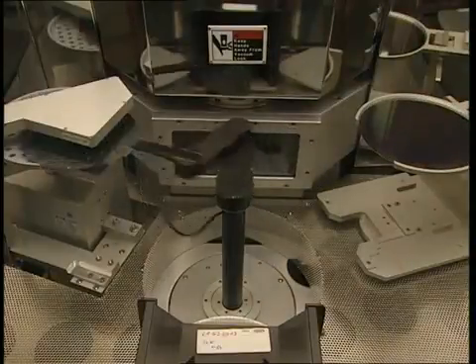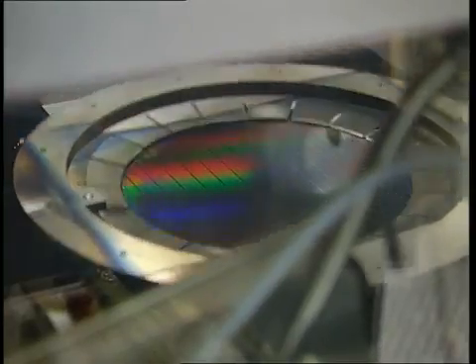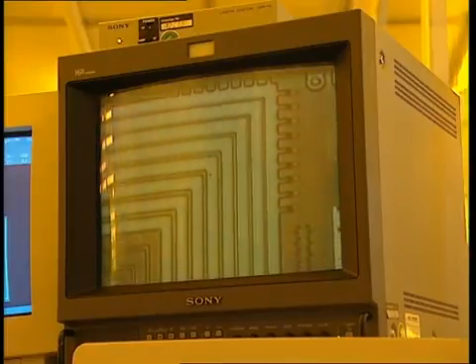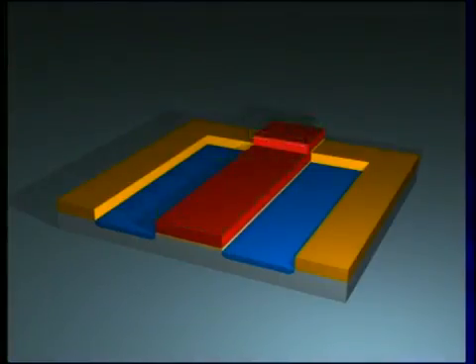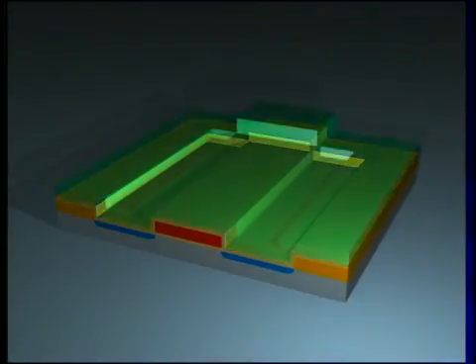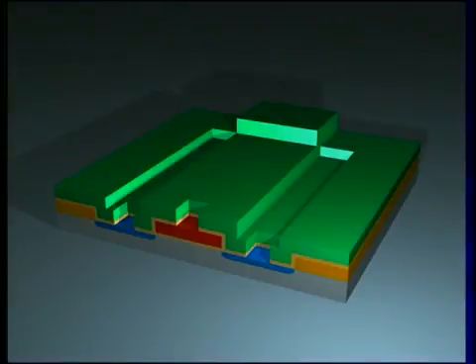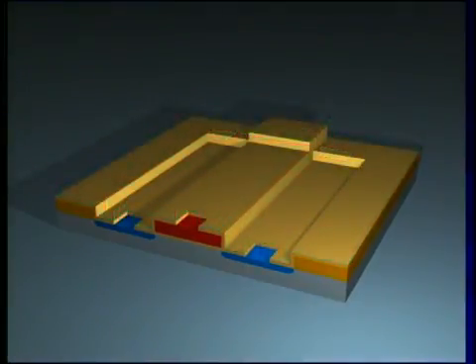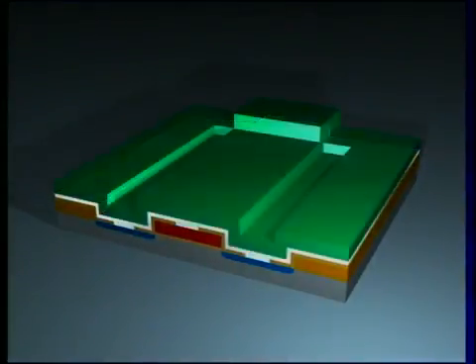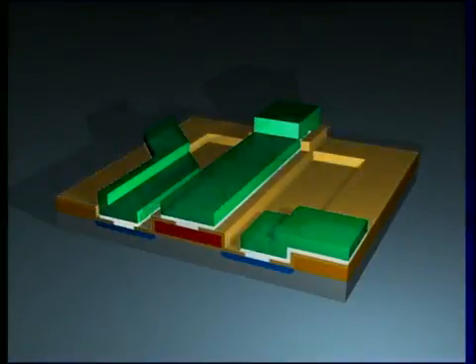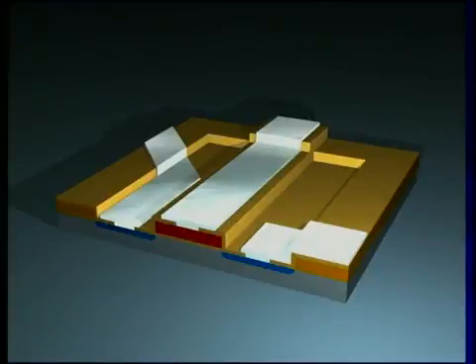The polysilicon and the thin oxide layer are etched off, remaining intact only in the middle under the resist layer. In the next step, an ion implanter shoots impurity atoms into the silicon, changing the conductivity of the exposed silicon by fractions of a micrometer. Structure widths, distances and cover precision are constantly checked. After the residual photoresist has been removed, another oxide layer is applied. The cycle of photoresist, exposure, removal and dissolution takes place again. Contact holes are etched in to open up access to the conductive layers because the contacts and interconnections must now be deposited. Metal compounds are sputtered onto the wafer in sputtering machines. Depending on the component, over 200 meters of interconnections are created. The unexposed strips show the path of the aluminum conductor tracks that remain behind after the etching process and provide contact to the underlying layers.